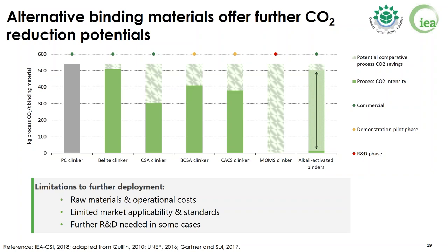Another limitation could be that there is not yet a market for the product, or the product has a limited applicability, and there are no standards and norms allowing for the use of the material. This is, for example, the case of BCSA clinker, that is Belite CSA clinker, and that is not yet accepted in norms and is not commercially produced accordingly. The same is the case of CACS, that is a cement based on carbonation of calcium silicate, and it also can sequester CO2 at the curing phase. But also this product, for the time being, has just a limited application, so it can only be used in precast. So the market currently is still rather limited.